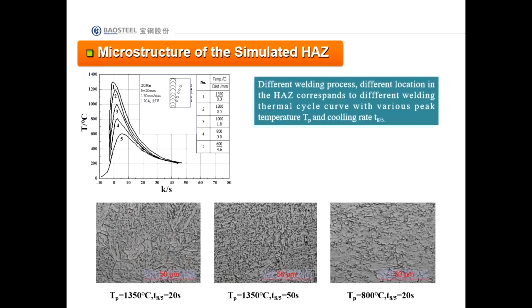The first is the microstructure of the simulated HAZ. We can simulate the microstructure of our interested location in the heat affected zone. The simulation temperature program takes different welding thermal cycles with different peak temperatures and different cooling rates.